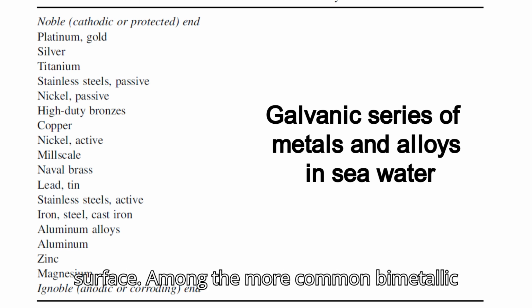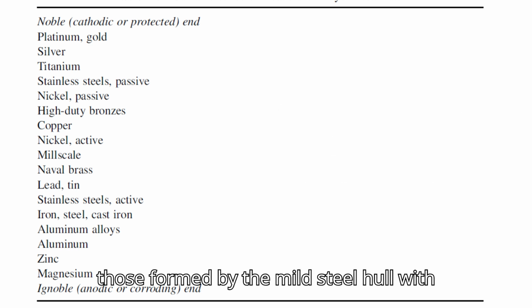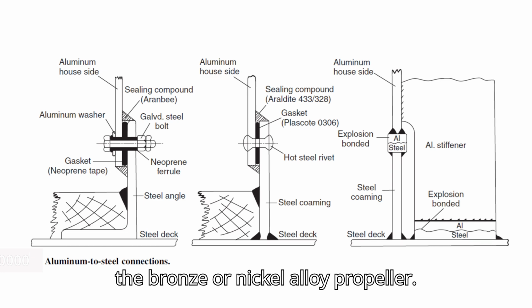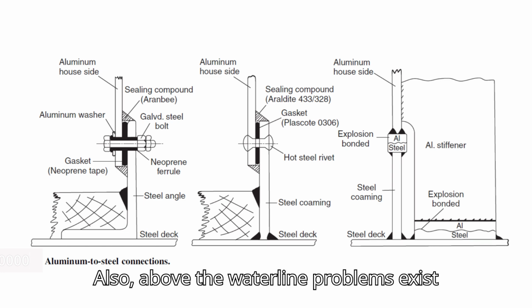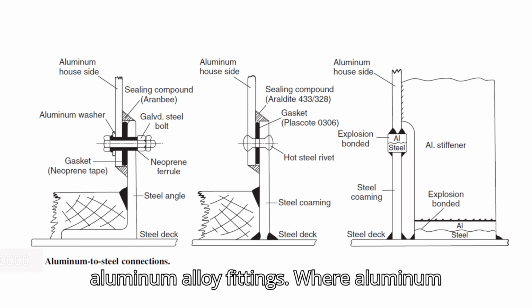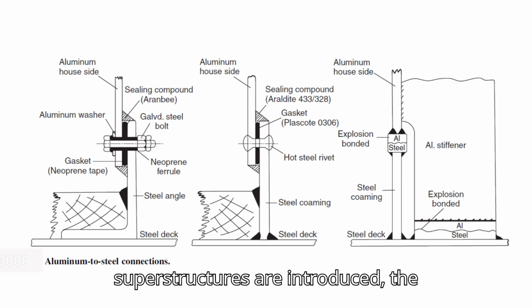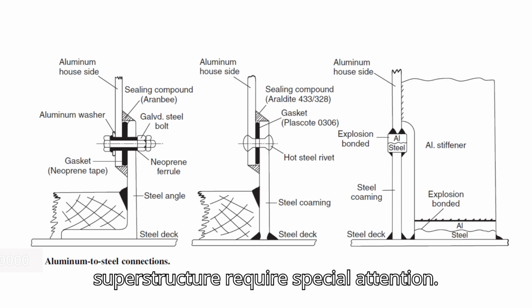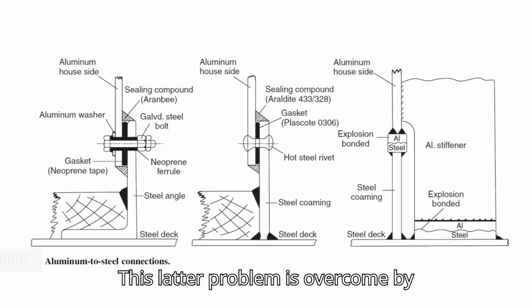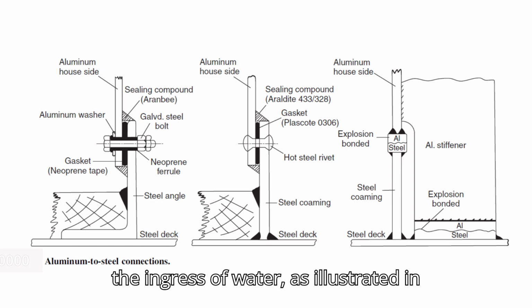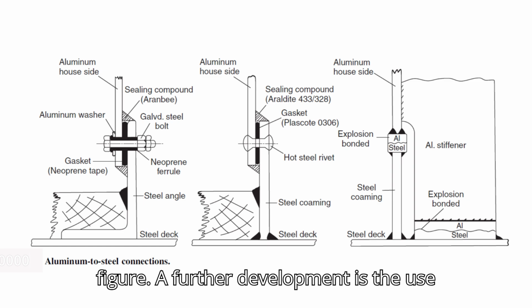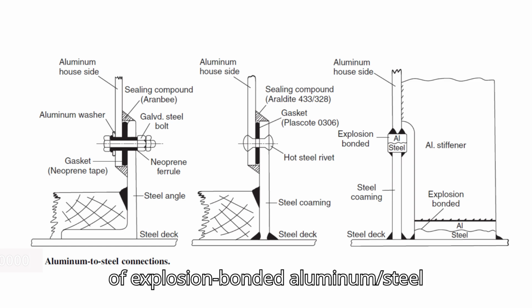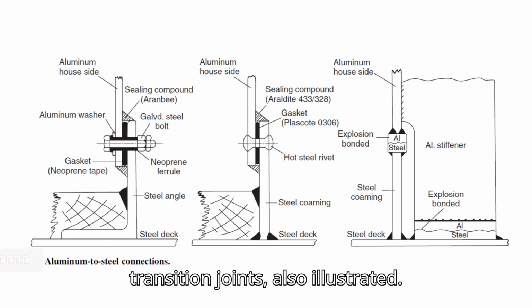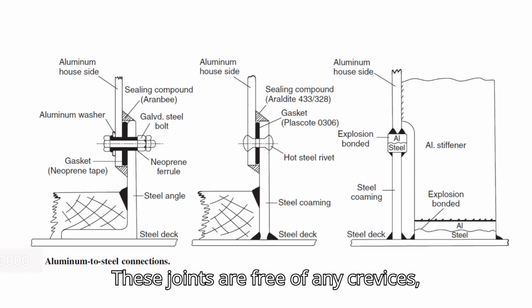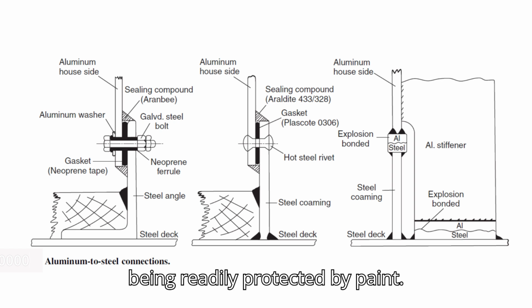Among the more common bimetallic corrosion cell problems in ship hulls are those formed by the mild steel hull with a bronze or nickel alloy propeller. Also, above the waterline problems exist with the attachment of bronze and aluminum alloy fittings. Where aluminum superstructures are introduced, the attachment to the steel hull and the fitting of steel equipment to the superstructure require special attention. This latter problem is overcome by insulating the two metals and preventing the ingress of water, as illustrated in the figure. A further development is the use of explosion-bonded aluminum/steel transition joints, also illustrated. These joints are free of any crevices, the exposed aluminum to steel interface being readily protected by paint.